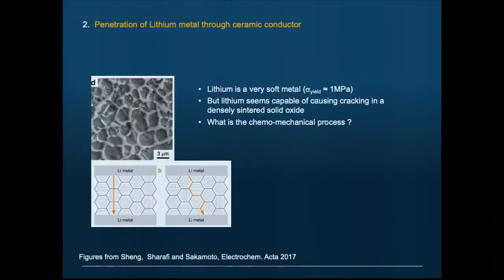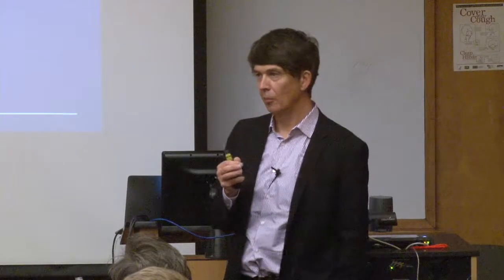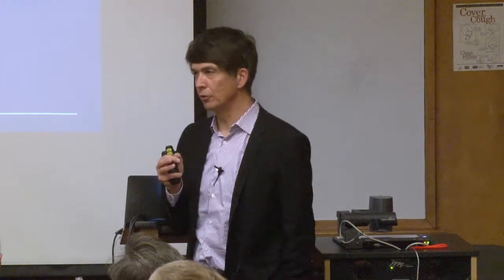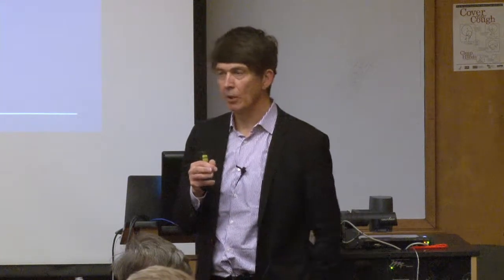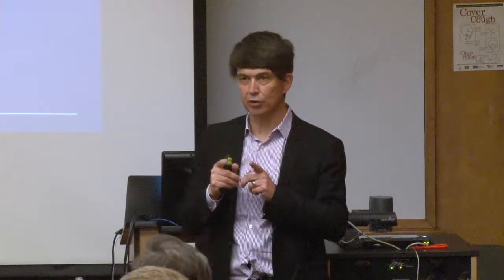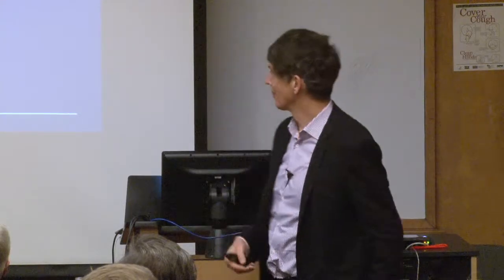The other one is, to make this worth our while, we also want to go to a lithium metal anode, right? Today we use graphite, but if we can go to lithium metal, we don't use lithium metal today in lithium-ion batteries for safety, because lithium tends to easily form dendrites when it's plated, and it sort of just makes a dendrite, and it short circuits to the other electrode. People have this belief that in solids, because solids are hard, lithium is a really soft metal. The yield strength of lithium is like 0.7 megapascal. It's a little above butter, right? And so people believe that if you put a hard solid in between the electrodes, lithium will not get through it, and so you won't have shorting. Well, that's what we thought.